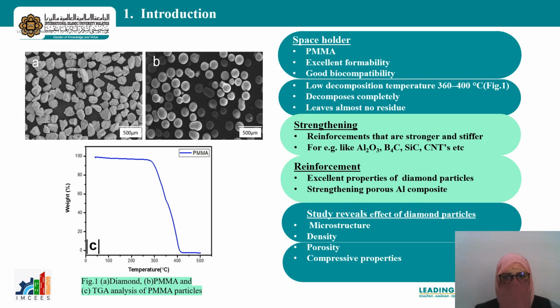Researchers have used many reinforcements in order to strengthen the composites, like alumina, boron carbide, silicon carbide, and carbon nanotubes. But in this study, we are going to use diamond particles as strengthening materials for porous aluminium composites. And we are going to study the microstructure, density, porosity, and compressive properties of these materials. As can be seen, figure C shows the TGA analysis of the PMMA particles, which shows the decomposition range. Figure A shows the diamond particles, and B shows the spherical PMMA particles.